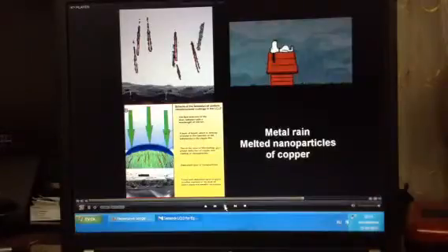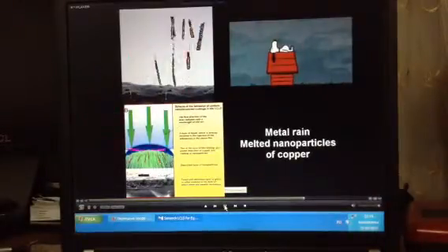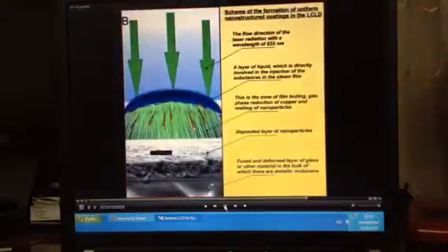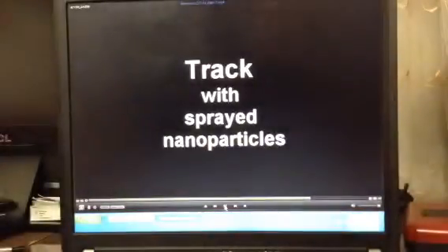And in this way, those particles form nanocoatings and homogeneous monolayers of nanoparticles. Okay. And there are many tracks consisting entirely of sprayed nanoparticles. For example, this is one of them. It's a track formed by LCLD, around 55 micrometers wide, with a very homogeneous surface consisting of spherical nanoparticles, nanoballs, with diameter around